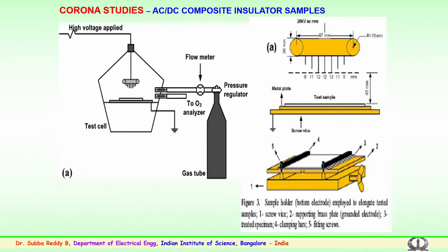Corona studies are carried out for both AC and DC on composite or polymer insulator samples. It is normally conducted in an experimental test cell, where corona is intentionally produced with corona needles. Various types of needles could be used, either circular needles which are uniform in nature, or non-uniform needles which look like a comb type of electrodes. So, uniform or non-uniform corona can be simulated by properly selecting the needles, and the test sample is kept here and high voltage is applied continuously.